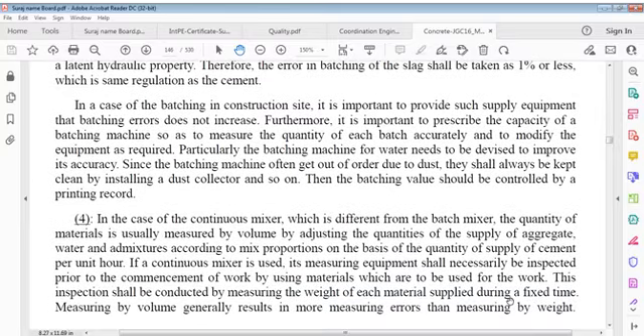In case of batching in construction site, it is important to provide such supply equipment that batching error does not increase. Furthermore, it is important to prescribe capacity of a batching machine so as to measure quantity of each batch accurately and to modify equipment as required. Particularly, batching machine for water needs to be devised to improve its accuracy. Since batching machines often get out of order due to dust, these shall always be kept clean by installing a dust collector and so on. And batching value should be controlled by printing record.